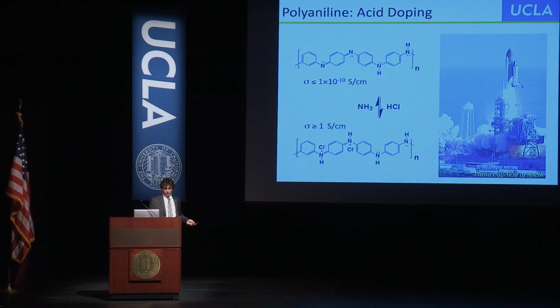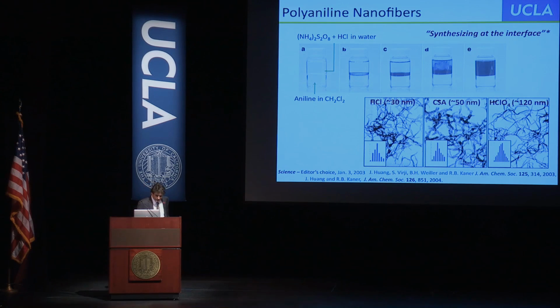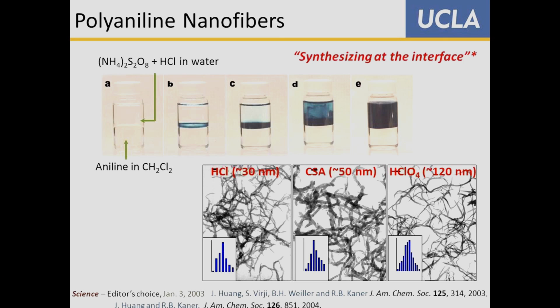So I met with my research group, and one of my graduate students said, don't worry, I'll make some nanoform of the material, and we can speed up this reaction. And so what we did is we did an interfacial polymerization. This is, you can make nylon by this method. But basically, we took aniline, this cheap starting material that comes from coal. We put it in an organic solvent. We took oxidizing agent and acid, put it here. And 30 seconds later at the interface, you can see the conducting polymer forming.